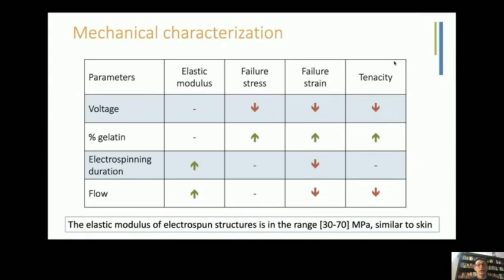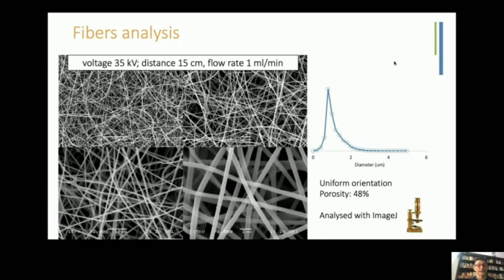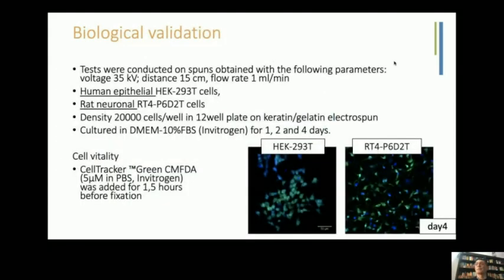As you can see from this table, all these parameters can alter the mechanical properties of the materials. So selecting the best parameters, we were able to obtain a structure that presents an elastic modulus between 30 and 70 megapascal. That is an elastic modulus similar to skin. And as you can see here, this fiber that was obtained presents a well-defined orientation, well-defined diameters in the range of 1.5 micrometers.